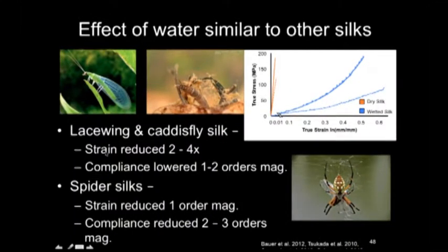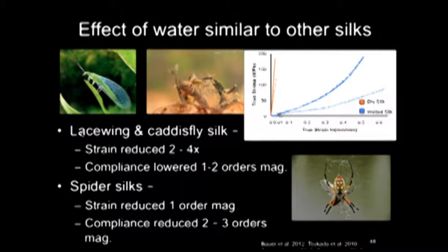So this is very similar to what we see in other silks from other types of animals. In insects, when wetted, silk strain, and this should actually say increase, but extensibility increases in wet conditions in both these lacewings that produce these stretchy egg stalks and caddisflies that build these casting nets underwater to catch prey, and spider silks as well, that when they're wet, we see an increase in extensibility as well as an increase in compliance. So water has these same effects: when they're dry, we see a reduction in extensibility and stiffening, but also we see increases in extensibility when wet.